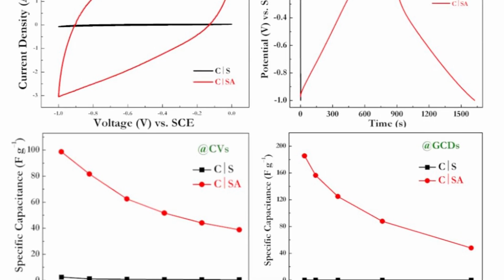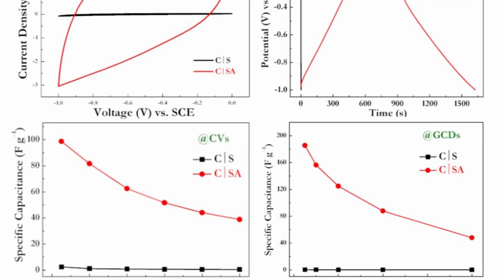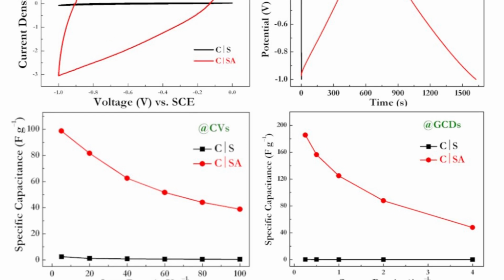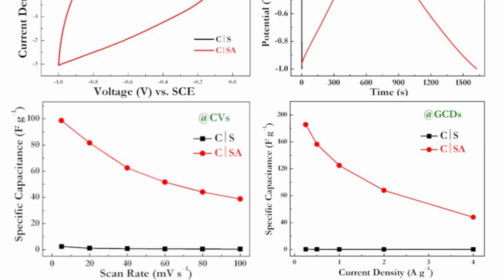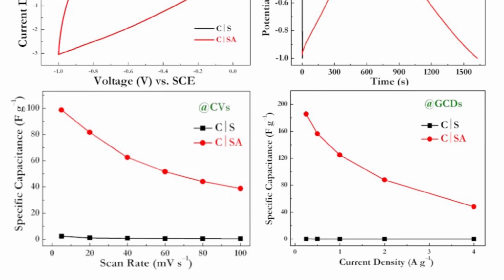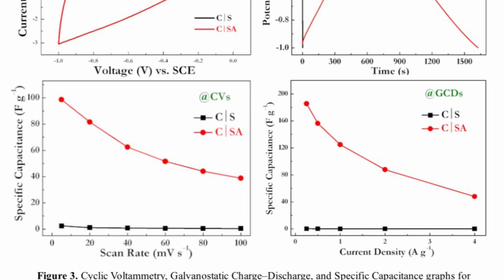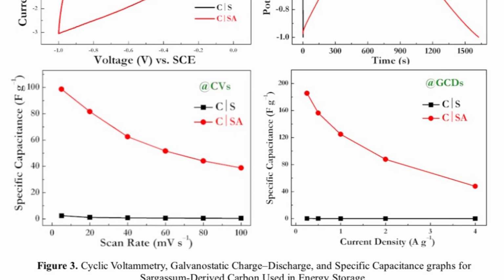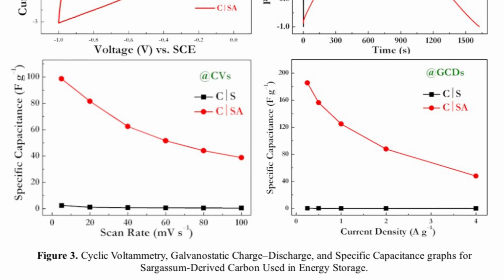The observed results from both tests show significant improvement in energy storage performance in the carbon derived from sargassum as an effect of chemical activating with KOH. This is then confirmed with the specific capacitance calculations.